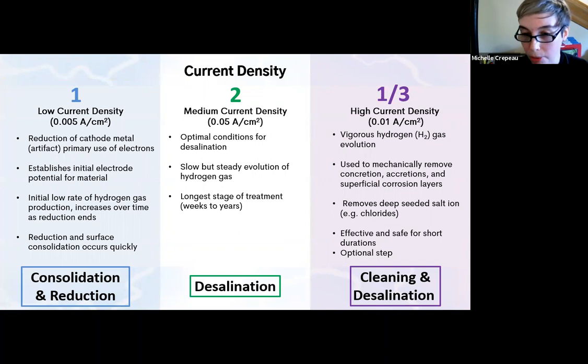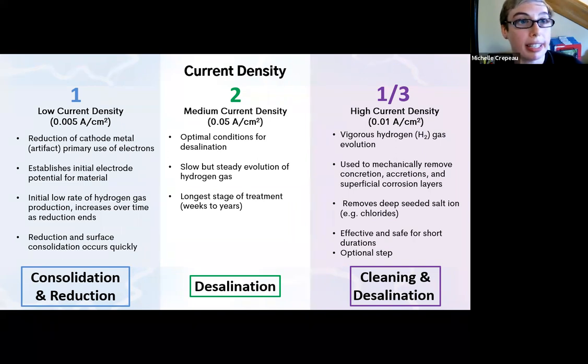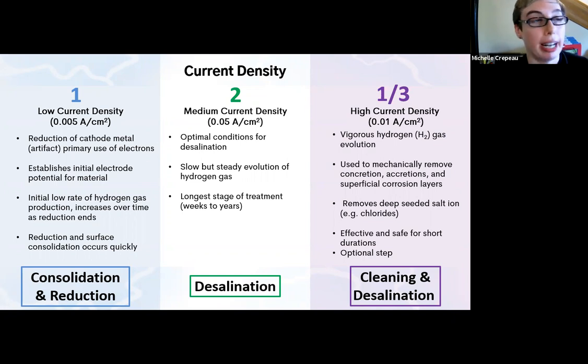Sometimes people will start with the high current density for a short period of time to try to remove some of the initial concretion material from the surface, and then quickly adjust it to a low current density, followed by medium current density. And then at the very end, you might use the high current density again, just to remove any residual chlorides and to finish cleaning the artifact. But oftentimes high current density is not used at all, just because there are dangers associated with it, which I will get to in a second.